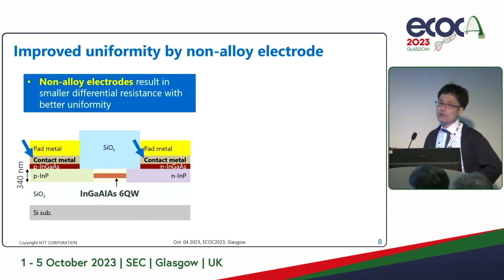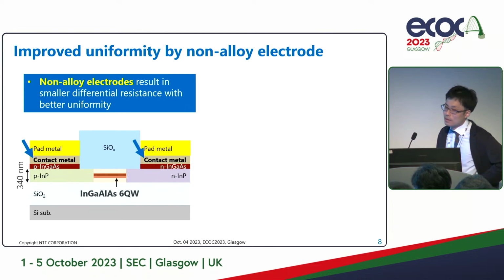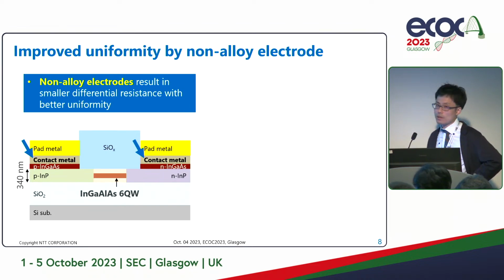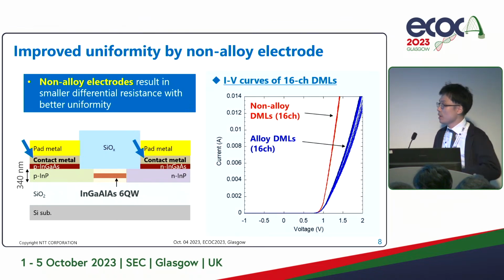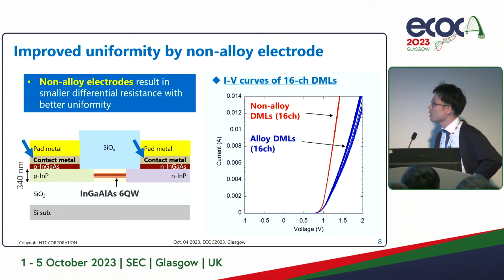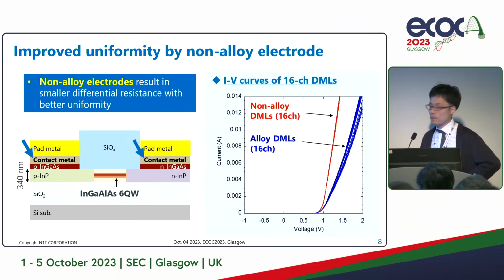On the left is a cross-section of our laser. The laser consists of an indium phosphide membrane. The thickness is 340 nanometers, and the device is on silicon. There is a contact layer and a contact metal layer. This time, we newly adopted a non-alloy electrode as the contact metal material, and previously we used alloy metal. On the right compares the IV characteristics of 16 DML arrays with alloy and non-alloy electrodes. As you can see, non-alloy electrodes result in a smaller differential resistance with better uniformity.